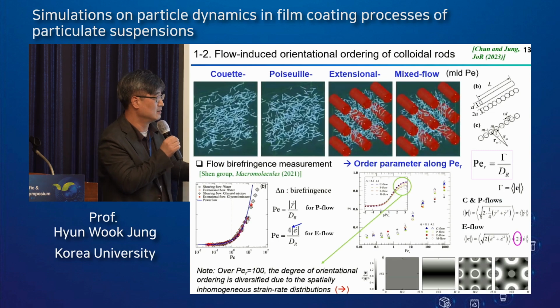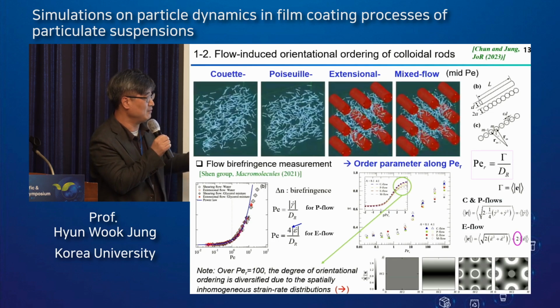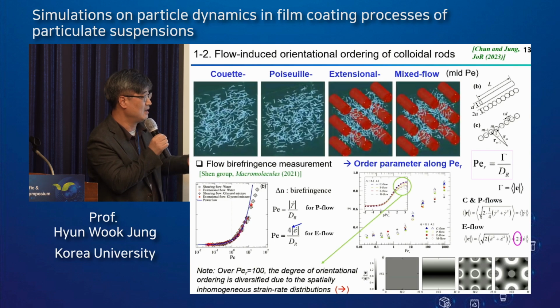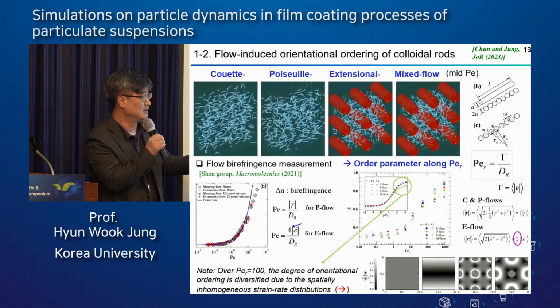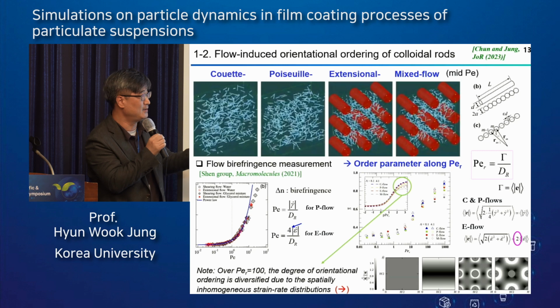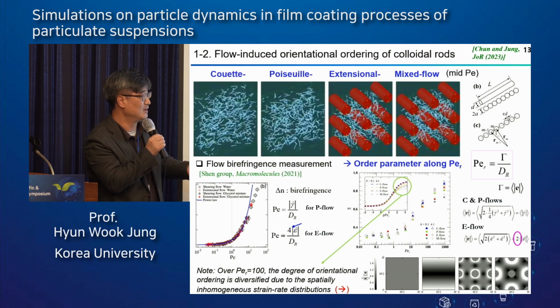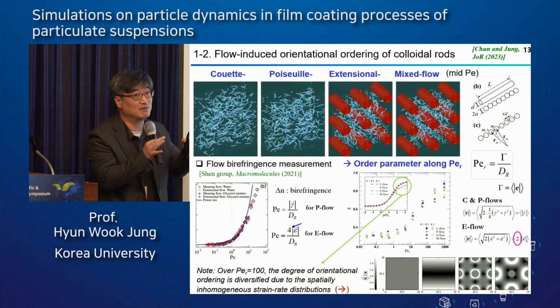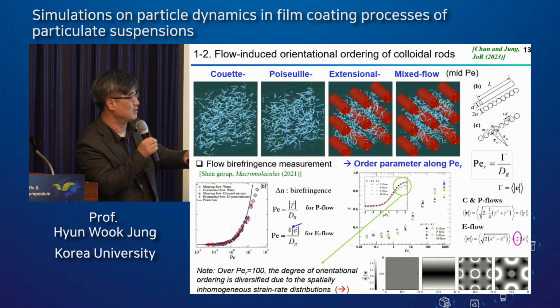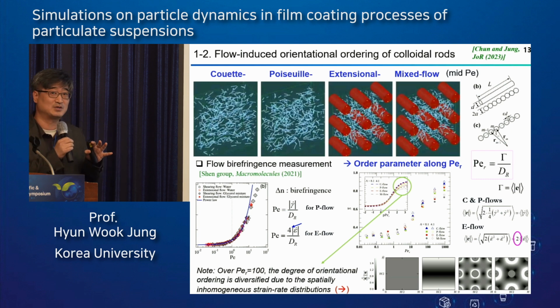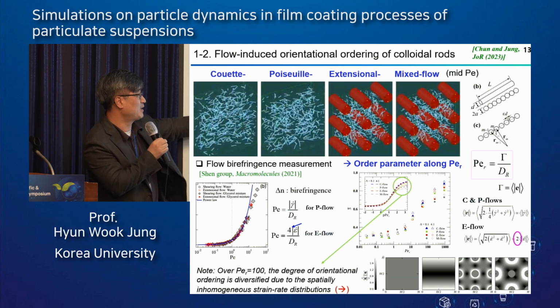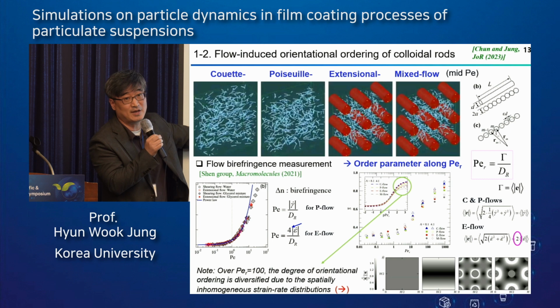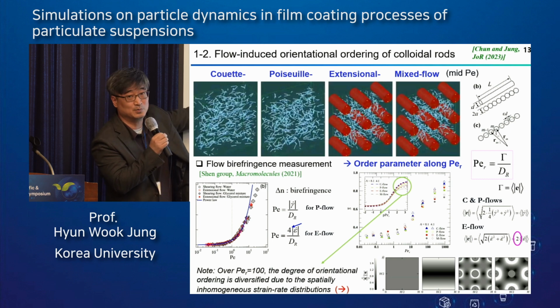Fortunately, we obtained one sigmoidal curve for the orientational order parameter along the Peclet number. So we found that the orientational order parameter increases with the rotational Peclet number regardless of flow field, a single master curve, except at the high Peclet number regime. Also, this simulation supported experimental birefringence data reported by another group.